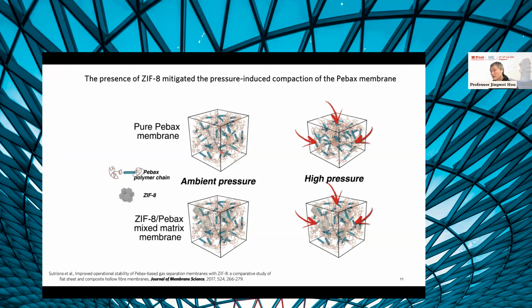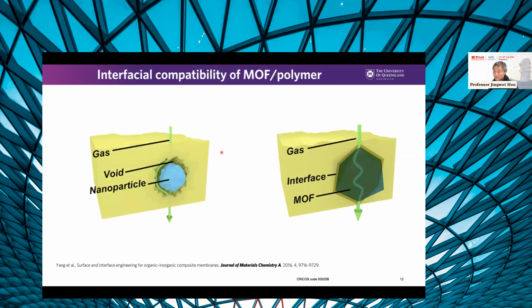So what happens if we incorporate a benchmark MOF, ZIF-8, into the polymer? Because there are so many chemistries in the MOF as well as the polymer, they can form a lot of hydrogen bondings between the crystal and the polymer. That actually gives additional mechanical strength at the molecular level for the composite, making the membrane much more robust and much more durable, particularly against high pressure. In this paper, we actually tested the membrane in the lab up to 35 bars. And the composite membrane still survives and can keep the original permeance after pressurization and depressurization cycles, which was really, really exciting.